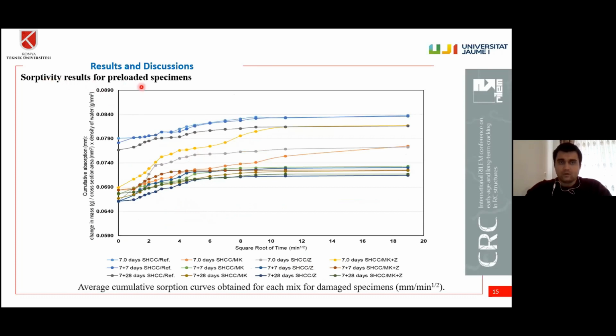This is for the preloaded specimens. As you can see, first, on the preloading day, the specimens having mineral admixtures had the lowest sorptivity index. But once the curing age starts, as you can see here and can follow with the yellow, brown, and green lines, the zeolite bearing specimens reduce the sorptivity index compared to other specimens, especially the reference specimens, as you can see from the trend lines.